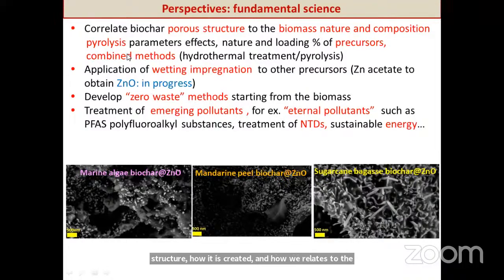Of course, we are interested now in the pyrolysis parameters effect, and we are submitting a new paper on this aspect probably today or tomorrow in the Journal of Analytical and Applied Pyrolysis. We would like to understand also the nature and loading of the precursor. As I have shown earlier, we see that nickel imparts some significant porosity to the biomass.